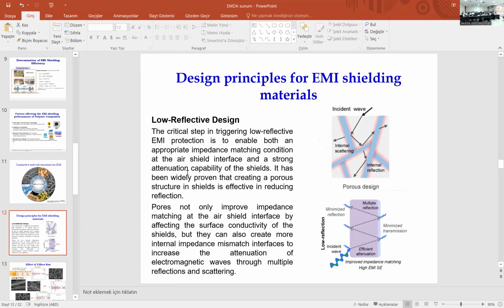And low reflective design is an important design parameter for polymer composites. Pores improve the impedance matching at the air-shield interfaces by affecting the surface conductivity of the shields, and they also create more internal impedance mismatch interfaces to increase the attenuation of the electromagnetic waves through multiple reflection and scattering.